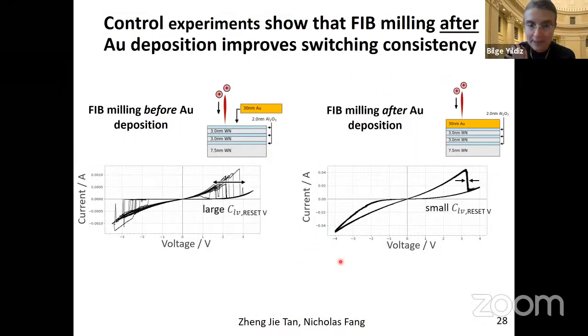So let's see what we mean. If you look at these current voltage curves, if you do not mill through gold, you get very large variability on the set, reset, on the amount of resistances. It's all over the place, like it's not a usable device. But if you mill through the gold layer, the cycling becomes very repeatable. And this is the ideal signature that you want to obtain. Okay, so something happens when you mill through the gold.